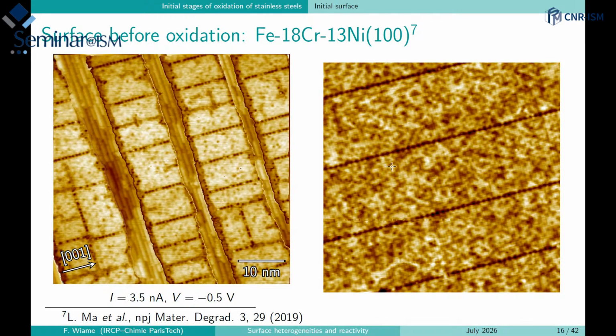You can see also some chemical contrast because we have iron, chromium, and nickel at the surface. So they will give some chemical contrast, some different intensity in the STM image, and we can also clearly see now the vacancy lines, which are much deeper than the corrugation at the surface.